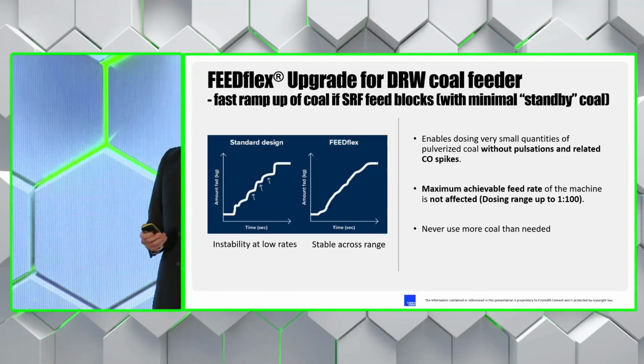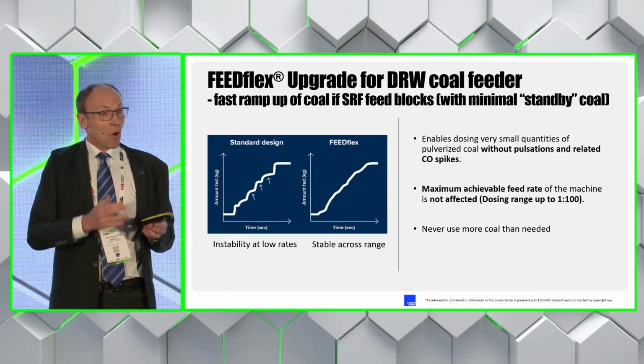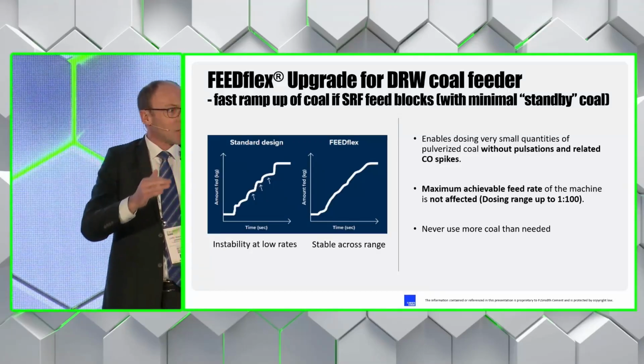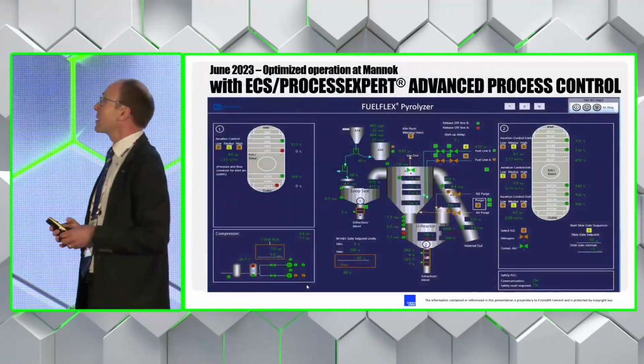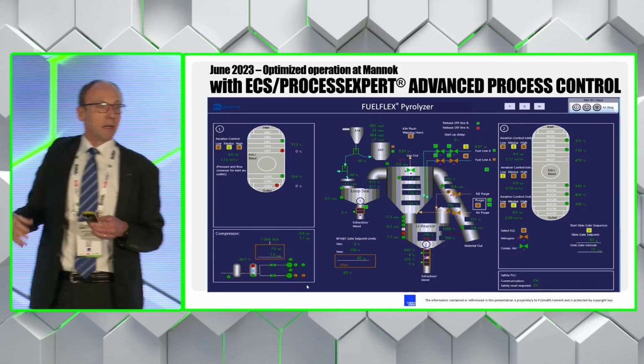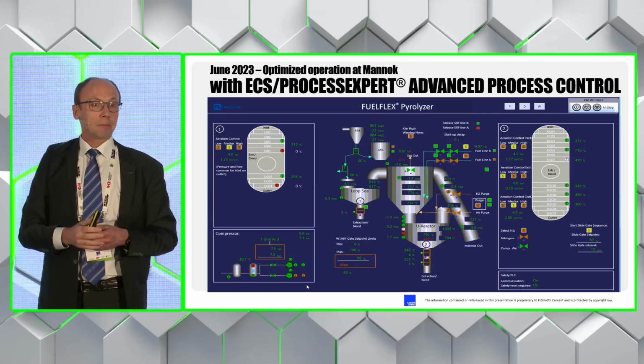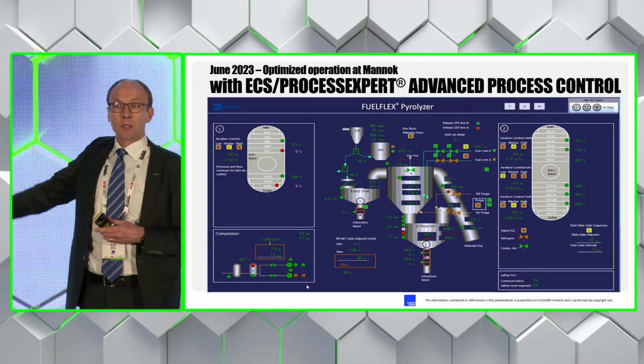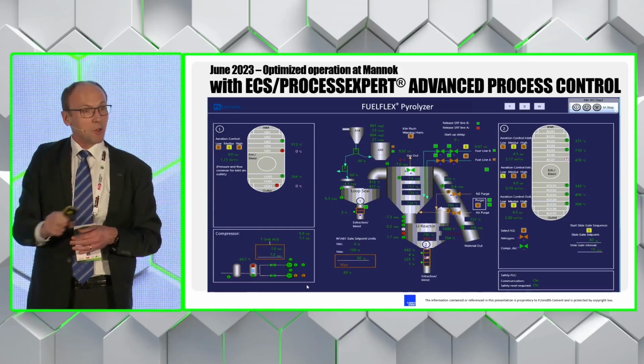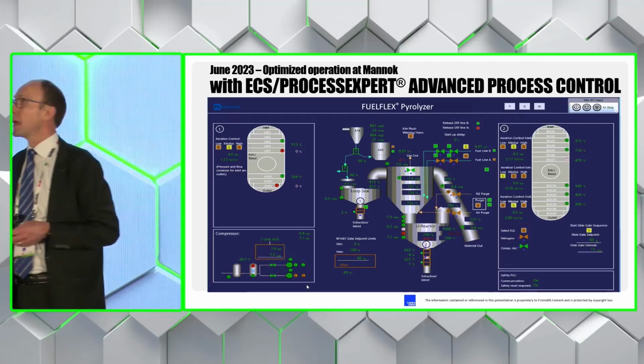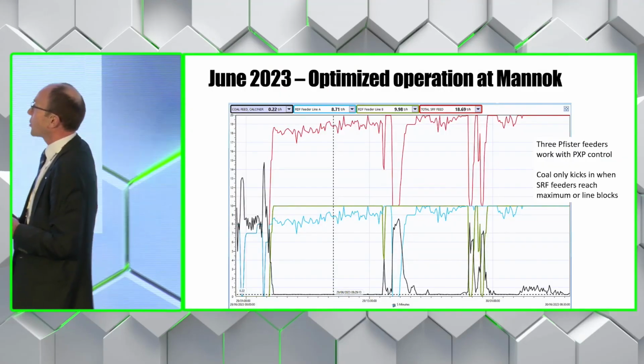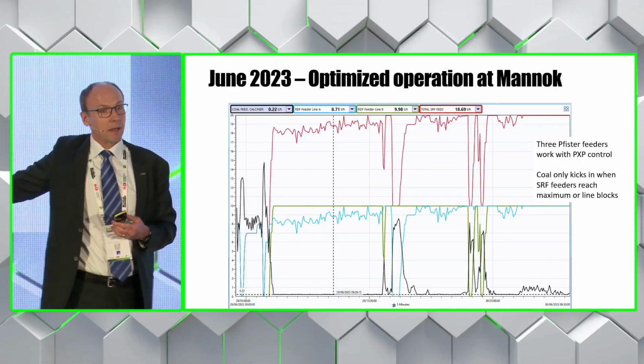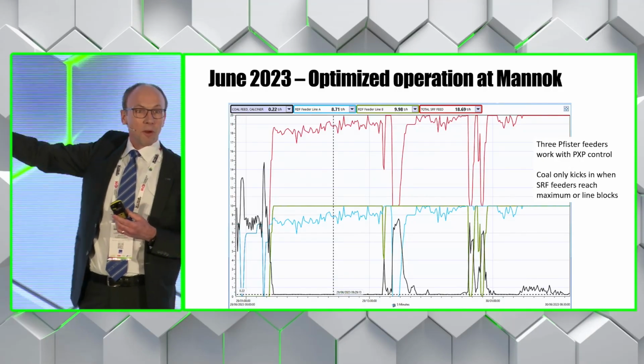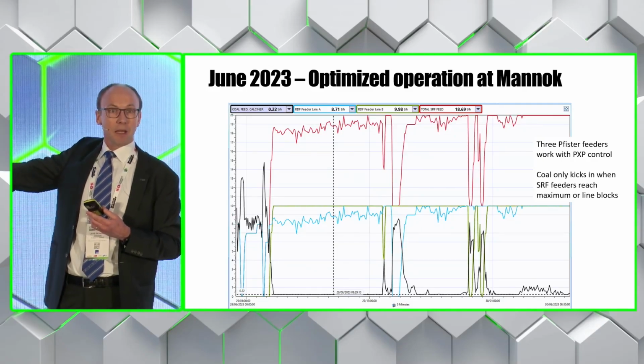minimal coal. The next challenge was now to ensure that the operators did this whenever possible to minimize the coal to an absolute minimum. And to do this, they upgraded their PXP process control system, and with this we were able to maintain the coal firing at an absolute minimum and still control the process very well. This is actually illustrated quite well by this chart over here, where the black lines are the coal firing, the blue lines are the alternative fuel firing directly to the calciner, and the green lines is the alternative fuel going to the FUELFLEX Pyrolyzer. The red line is then the total alternative fuel going to the calciner.